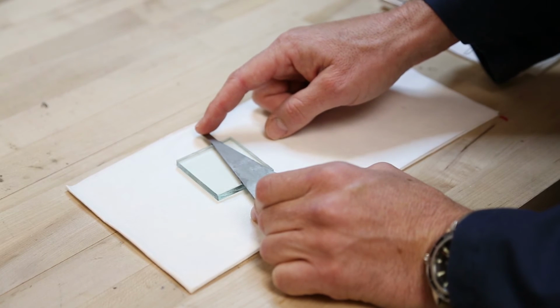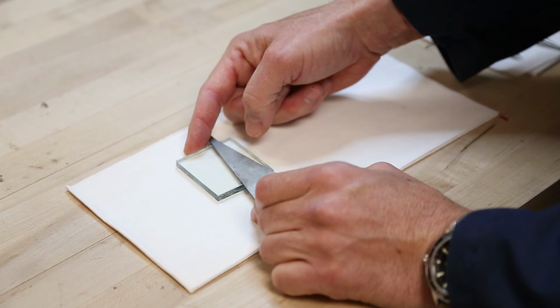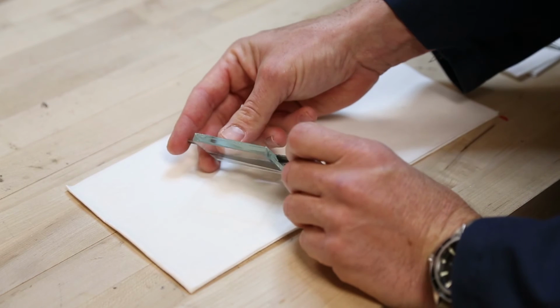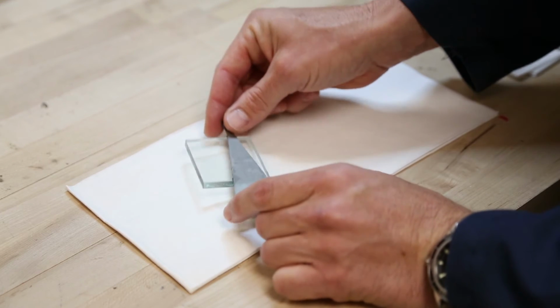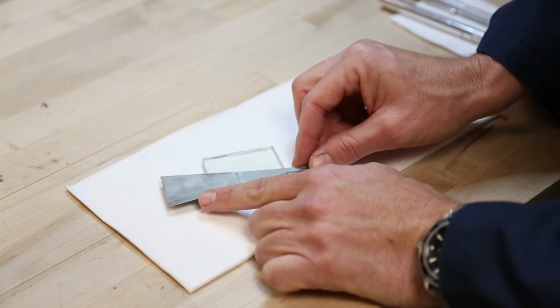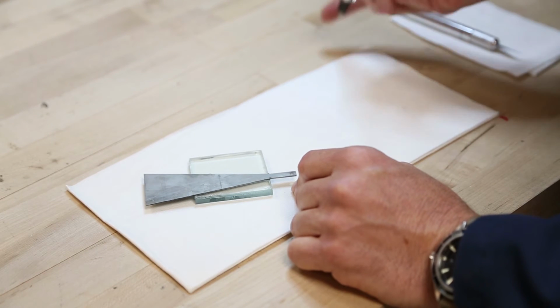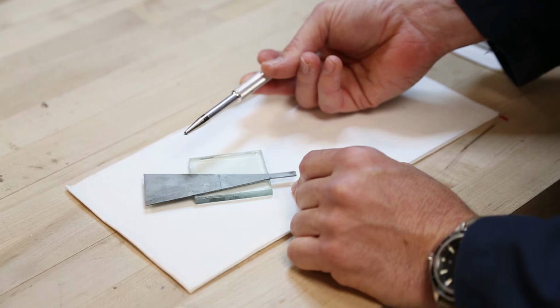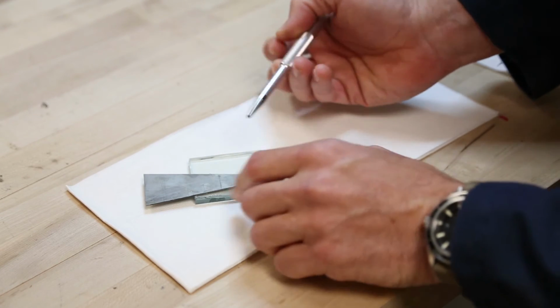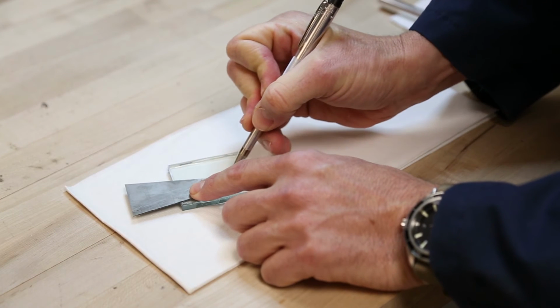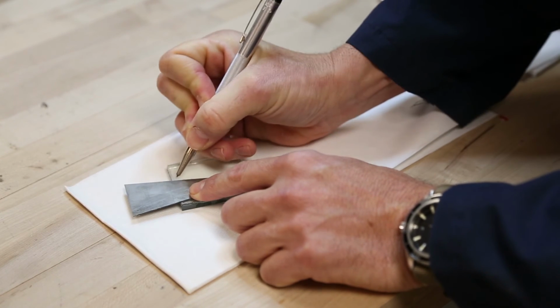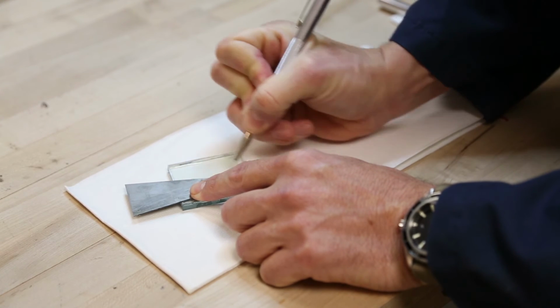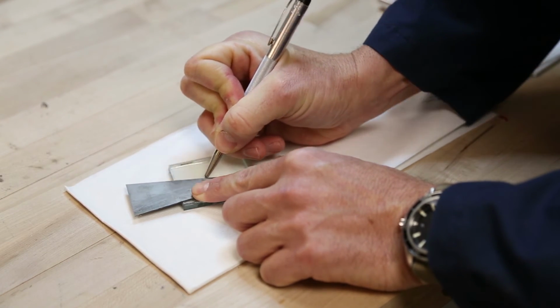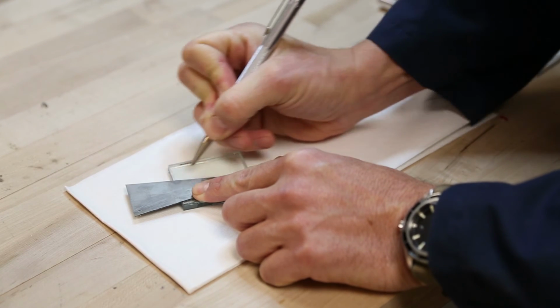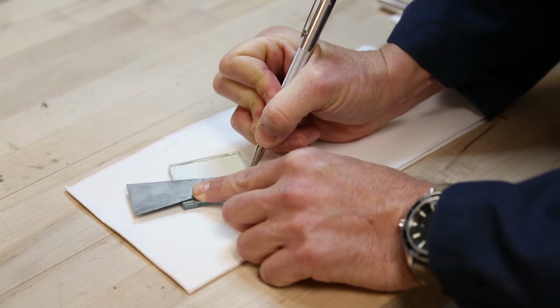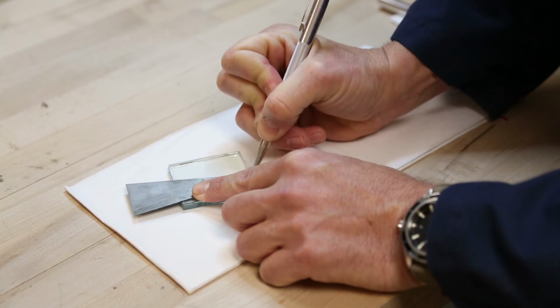This is, again, the titanium beam, epoxied to a thin microscope slide that's in turn laminated with encapsulant to the thicker slide of glass. The first step in preparing for testing is to section through that thin microscope slide to release the beam. Again, I like to use a diamond or carbide scribe and grind through that thin 150 micron thick microscope slide. I use the beam as a guide with light pressure, and it's pretty easy to get through. And you'll feel the gummy encapsulant underneath once you break through.